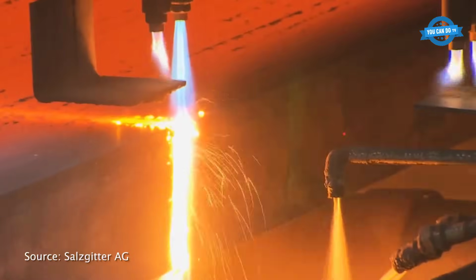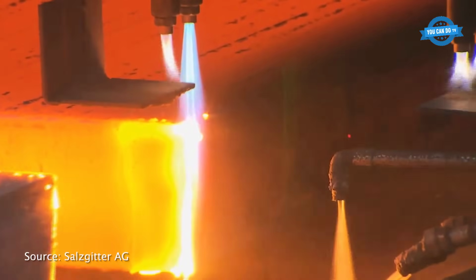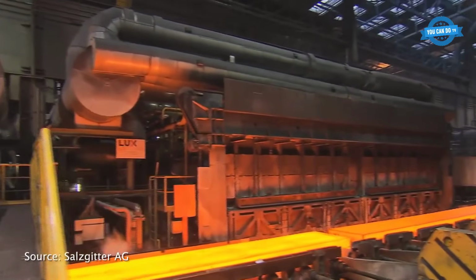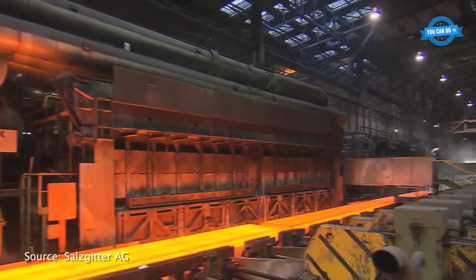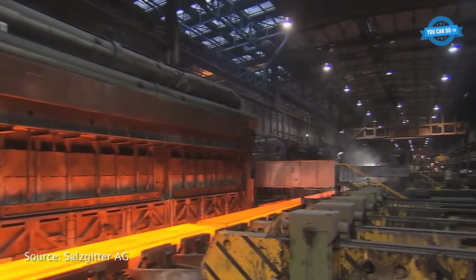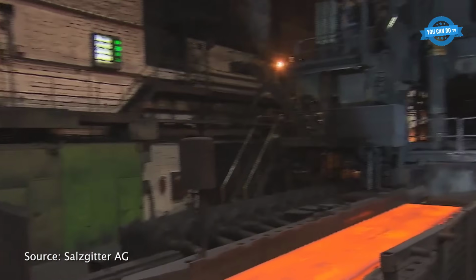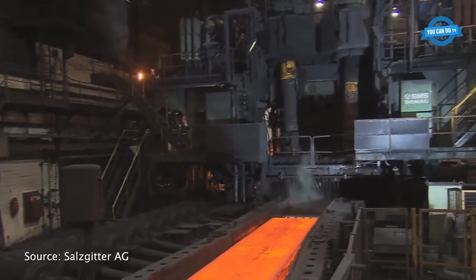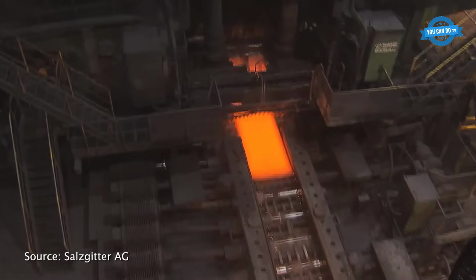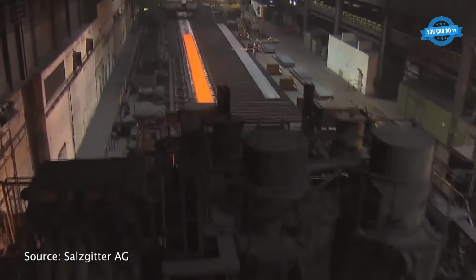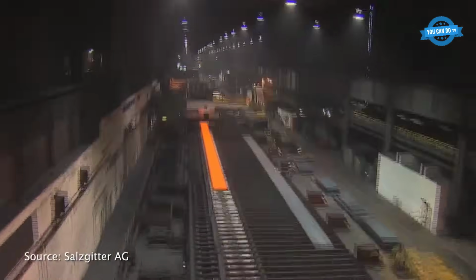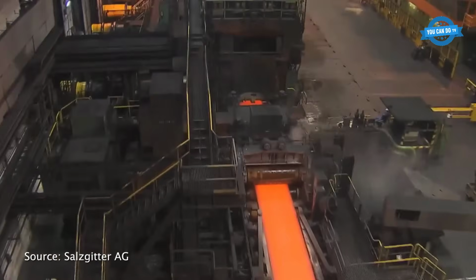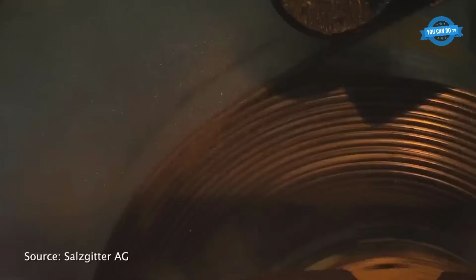At the plant, towering blast furnaces, some over 50 meters tall, process up to 14,000 tons of pig iron daily. Inside, layers of coke, ore, and limestone descend, heated by process gas generated from air blasted at 1,500 degrees Celsius. This reduces and melts the ore into molten iron and slag, tapped every 2 hours at 1,450 degrees Celsius.